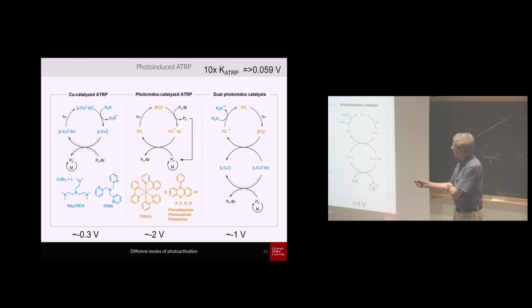So in that case, you can have a reaction of this photoexcited species with alkyl halide, reduce it to radical, and in a kind of magic way it gets deactivated somehow. The problem is that the lifetime of these photoexcited species is nanoseconds, or sometimes picoseconds. So you don't have them at a very high concentration, because otherwise you will have too many radicals. And then you have another class of species which would be also photoexcited, but they are not that reducing. They have a redox potential maybe negative 1 volt only. So it is enough to reduce copper-2 to copper-1, but not enough to send the electron to the alkyl halides.